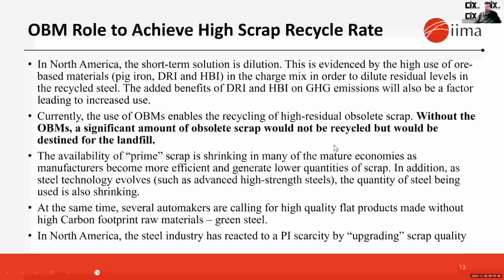So in North America, the short-term solution has been dilution. And so we are probably one of the largest users of ore-based metallics in the EAF. And we use those to dilute the residuals. Without the ore-based metallics, a significant amount of obsolete scrap will reach a point where it can't be recycled at all. And the reality is that the availability of prime scrap is shrinking in many of the mature economies, because manufacturers always want to become more and more efficient. And so they're trying to generate lower and lower quantities of scrap. So obviously the amount that can be recycled back to the steelmaker is shrinking.